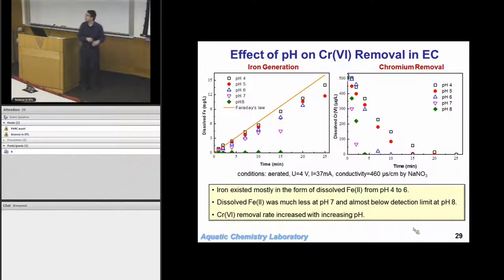Still works, but not quite as fast. And this is because those reaction rates are very pH dependent. In particular, the dissolved iron 2 reaction rate is quite pH dependent. So we think that at low pH, we're primarily having what's called homogeneous reduction. At the higher pH values, we're having heterogeneous reduction. And it's occurring faster because of that. But overall, it works quite well.